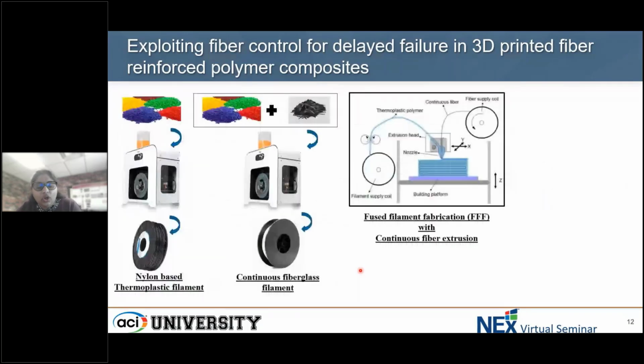So to get into the methodology itself, the process itself, we've used nylon-based thermoplastic filaments, and the fiber itself is a fiberglass filament. And the mechanism that we've used in the 3D printing technology is a continuous fiber extrusion, meaning this doesn't relate to chopped fiber. It is a mixture of the thermoplastic along with the chopped fiber that has been input into a filament maker, which makes a filament that has both a fiberglass component and a thermoplastic component. So this in itself is a fiber reinforced polymer.